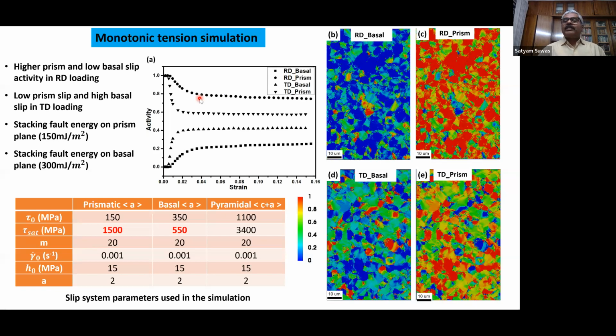Right. So after that, we could predict the activities. The slip activity maps are shown here. So for RD samples, the basal slip activities are shown here, right? The propensity of a particular slip activity is shown through this scale. The highest one is red. So here we could see some hot spots, red ones. And for prism slip, obviously it is the inverse, so it's minimal here. So it is basal dominated here, the red one.